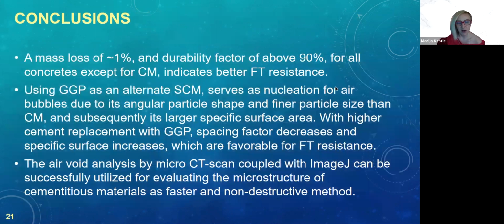And some conclusions made from this study. The mass loss was close to 1%, and durability factor was above 90% for all concretes except for cement, and that indicates better freeze-thaw resistance. Another conclusion that could be drawn is that using GGP as an alternative supplementary cementitious material serves as nucleation for air bubbles due to its angular particle shape and finer particle size than cement, and subsequently its larger specific surface area. So with the higher cement replacement with GGP, spacing factor decreases and specific surface increases, which is favorable for freeze-thaw resistance.